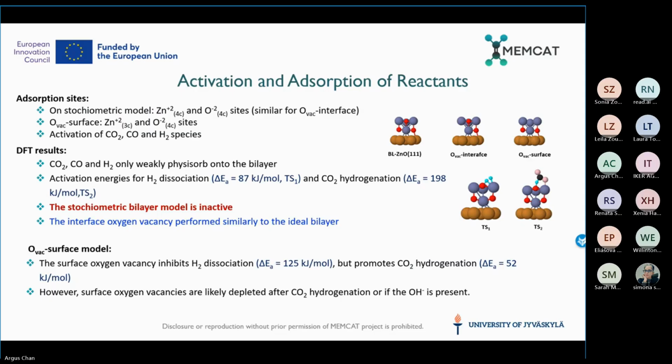If we include vacancies, then we find that this bilayer, in the presence of the vacancy, is not very active towards H2 dissociation, while the hydrogenation of CO2 is more energetically favorable. But then the question is, how about under reaction conditions? Do we really have oxygen vacancies? And are there OH groups present? Because they can change the whole game.